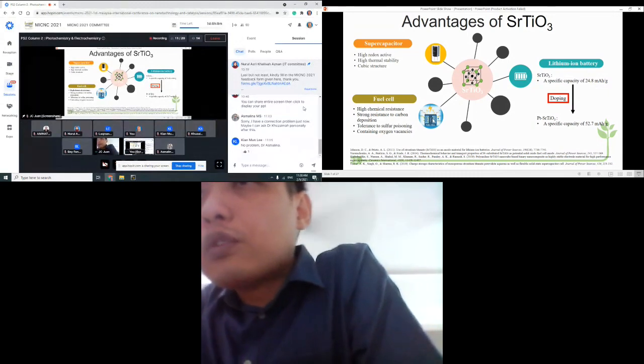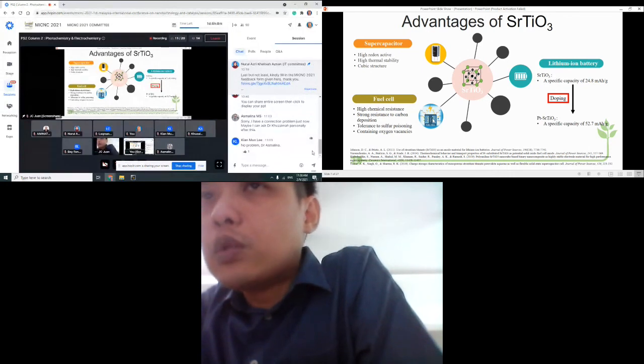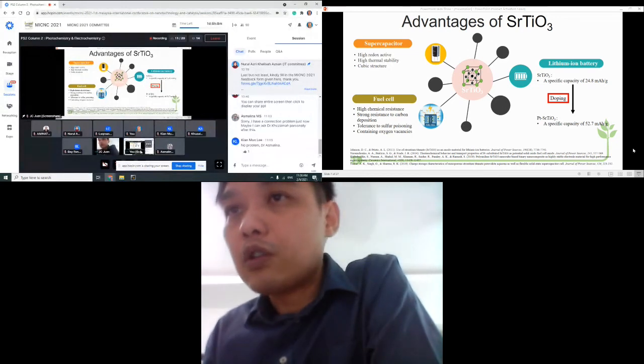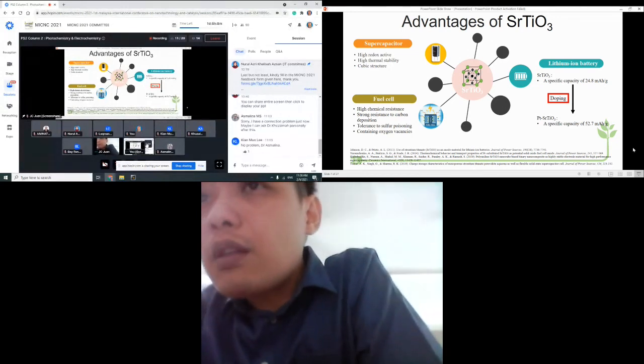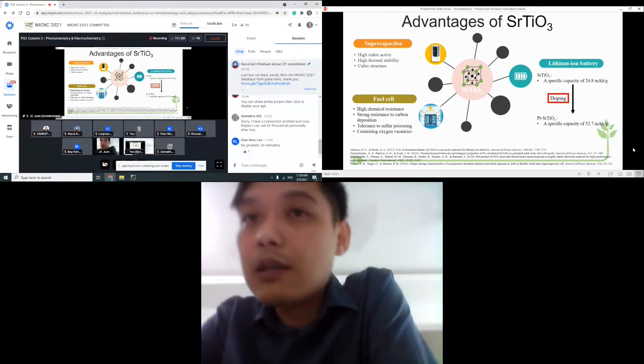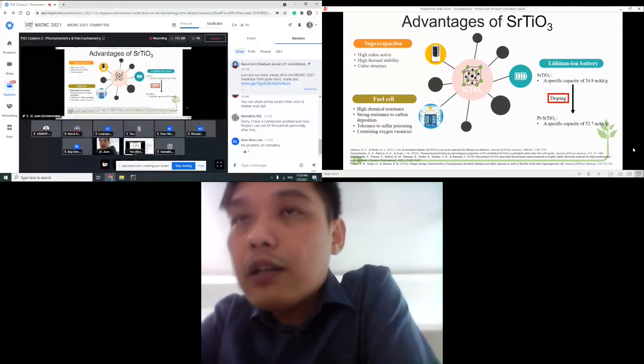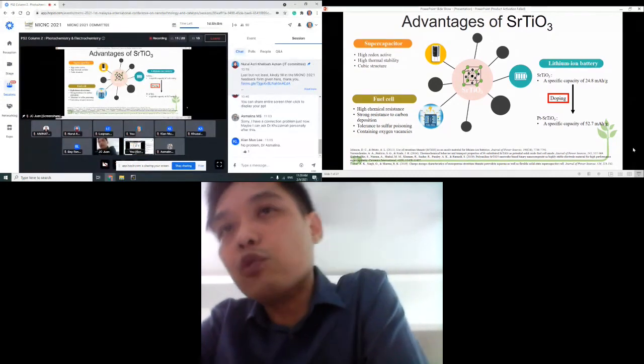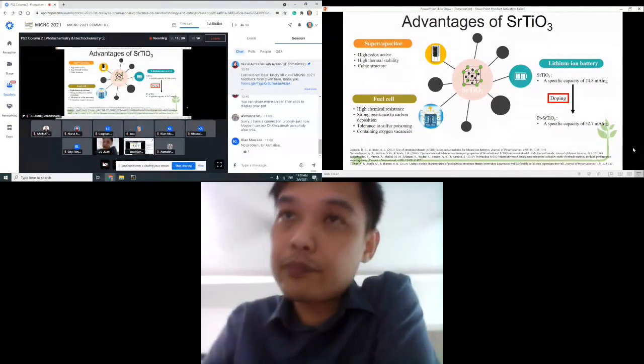So SrTiO3 has a specific capacity of 24.8. We have managed to use this SrTiO3 in our batteries, and what we need to do is some doping. In the literature, they mentioned that SrTiO3, with a specific capacity of 24.8, after doping with platinum, can increase to 52.7. So it's about 2 times. That means there is potential for us to further improve this SrTiO3 by using a dopant.